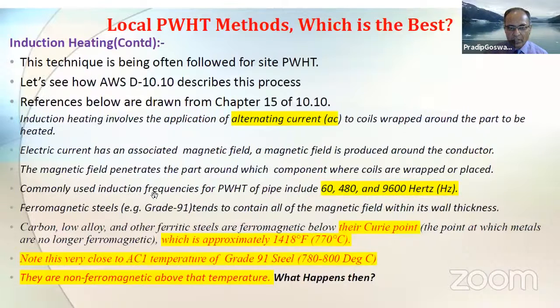Now, commonly used induction frequencies for post-weld heat treatment for pipes are typically 60, 480, and 9600 hertz. This is a typical frequency which one comes across when induction heating is concerned. Ferromagnetic steels, that is grade 91 steels, tend to contain all of the magnetic properties within its wall thickness.